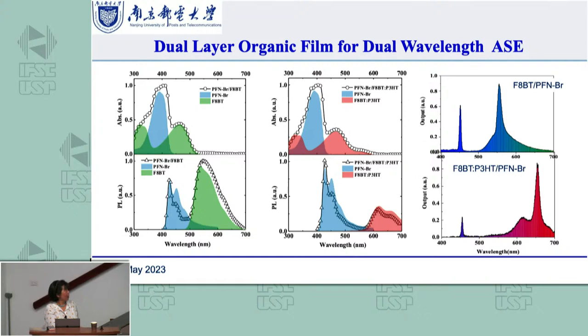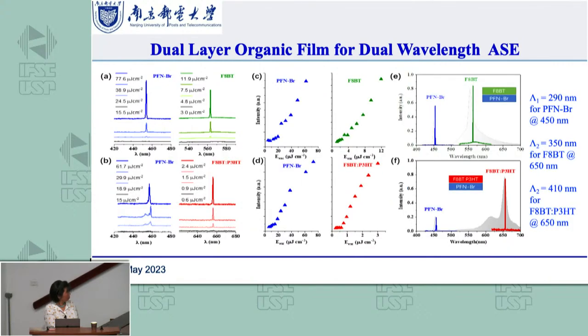After this test, we used a pump of about 390 nanometers wavelength and got the ASE from this system. Similarly, we pumped the red and blue system and got two ASE peaks. After that, we put this film on the grating substrate and got two laser peaks for this and for that.